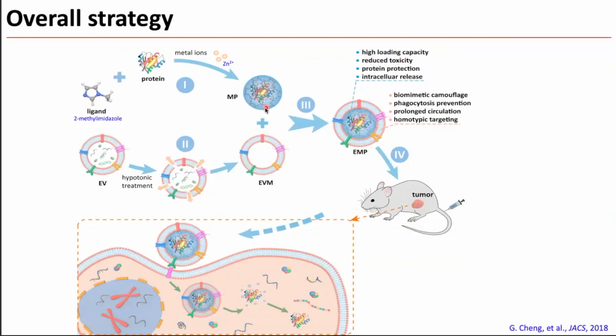The protein inside this nanoparticle is protected by the nanoparticle, so the protein is not accessible to degradation. And then we can achieve intracellular release because we designed this nanoparticle in a pH responsive way. Basically, if the pH is lowered, this nanoparticle will start to disintegrate so that the proteins will be released.